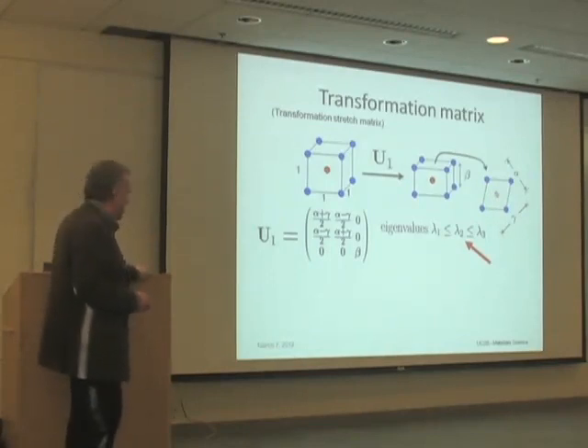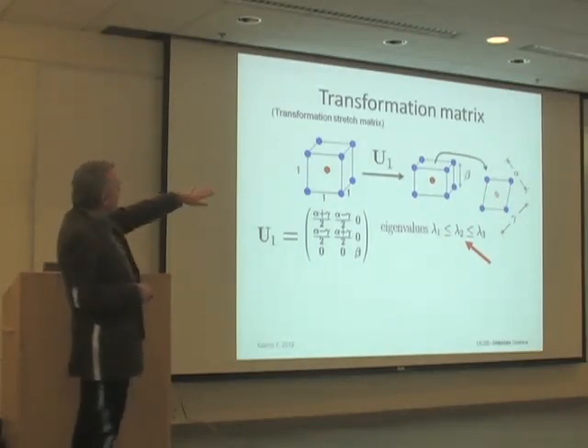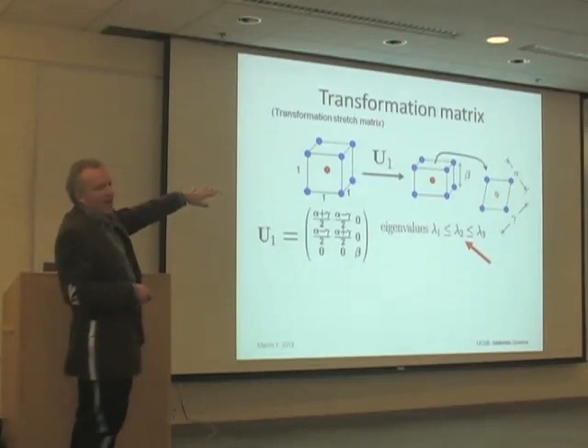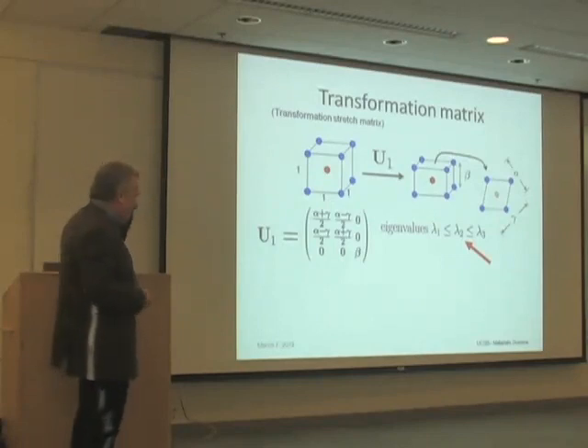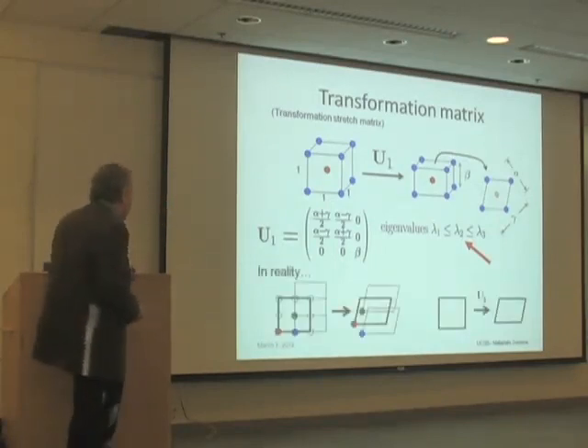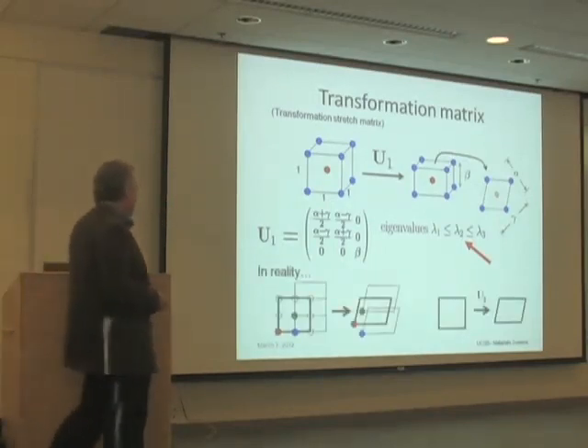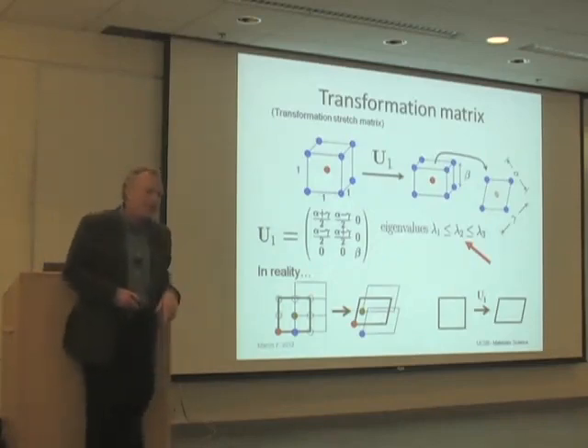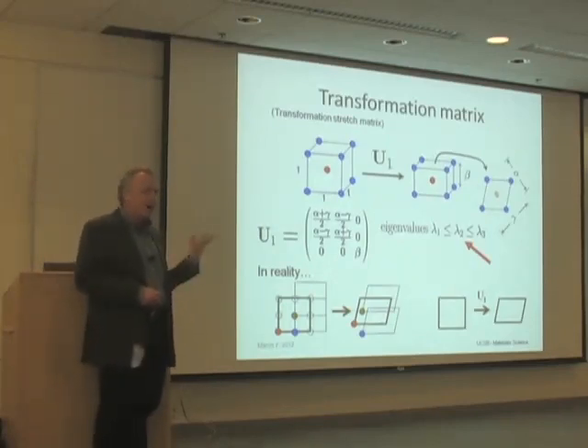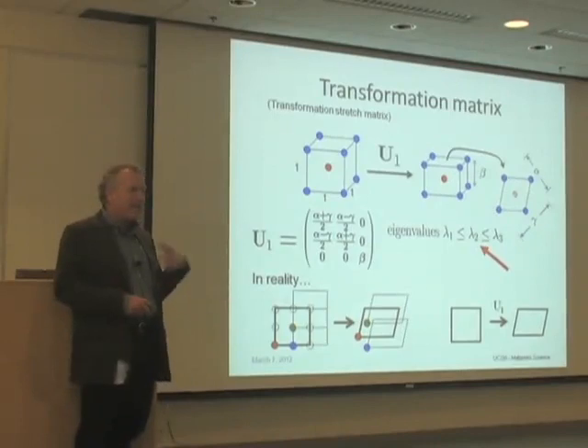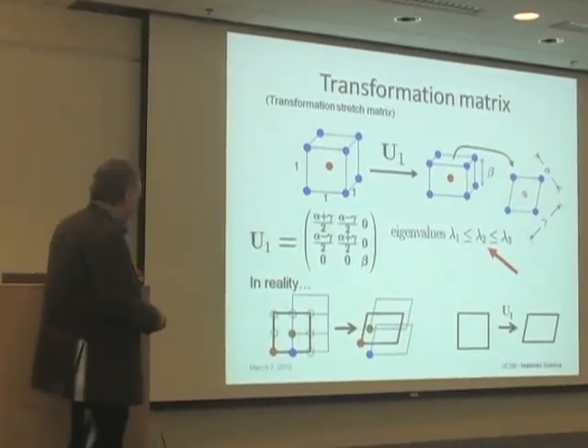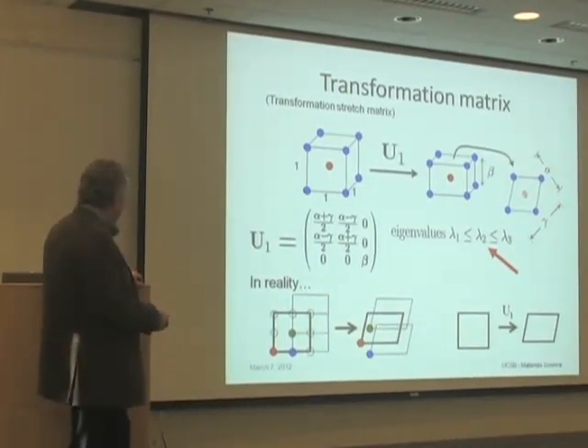So actually, this picture, this is a textbook picture of phase transformations. It almost never happens in real materials. Okay, what really happens in materials is this. Real materials, martensitic materials, are complex lattices. There's modulation, there's shuffling. So the real situation is this down here. There's a number of Bravais lattices. I pictured three of them here based at these three colored atoms. I drew it in two dimensions.